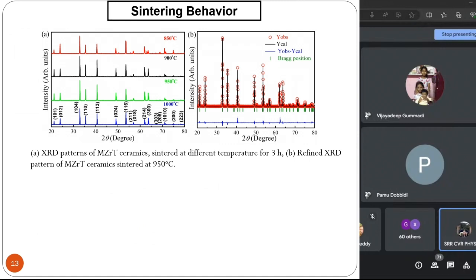And then what we have done is that we have sintered this material. Now we have only got the required phase for the material, but we need to compact them. That means if I want to say dielectric resonator, it is like your paracetamol tablet. So even if I drop it from 10 meters above to the floor, the material should not break. For that, we need to induce density in the material. If you want to induce the material density, you have to make a disc and fire it at a higher temperature.